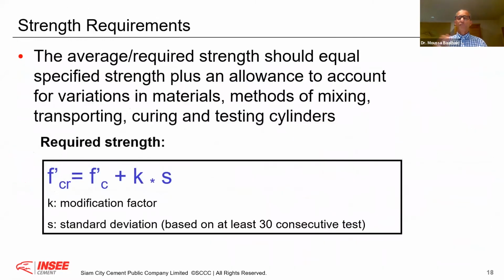Now, of course, as an engineer, when you design, the required strength should be higher than the specified. If I'm specifying 30 MPa, I have to take an allowance to take into consideration variation in materials. This is why, if you buy concrete, you need to buy it from a producer who has a very good quality assurance system, with a very good standard deviation, with enough consecutive tests for the mix he is developing for your project. That is important, so you have to take this into account. For example, in Sri Lanka, whenever you design 30, you request 40. I will explain why.